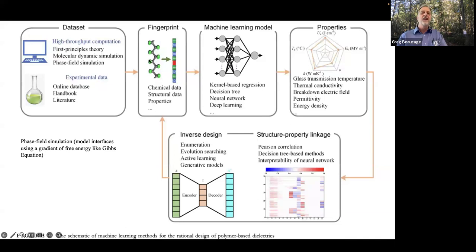So people spend a lot of time figuring out how to fingerprint. They call it fingerprinting the polymer. So basically you can turn that structure into like a code, right? So basically you can feed all the possibilities of producing the polymer. So you'll label your data with these fingerprints of what the polymer was that went into it, and also the fingerprint of what the inorganic component is, and the fingerprint of the composite, and maybe a fingerprint of the structure, like what's the structural arrangement of the chemical components that went in.